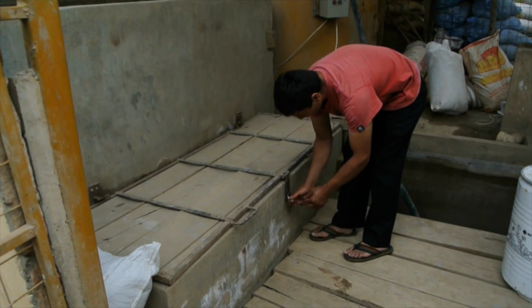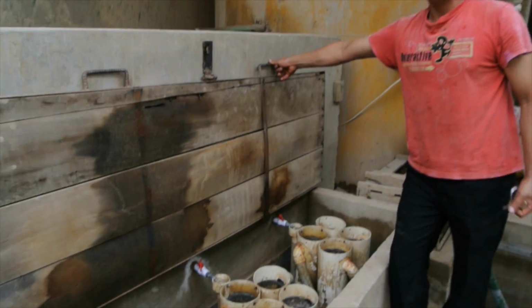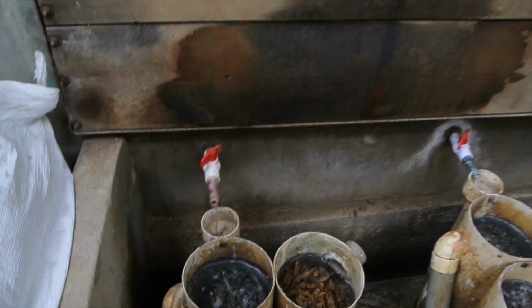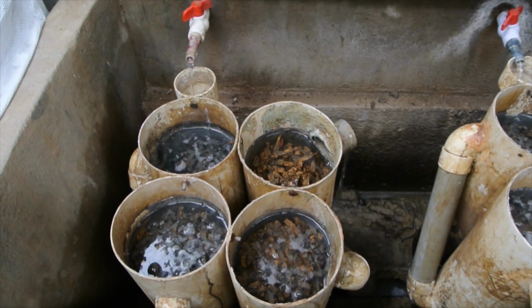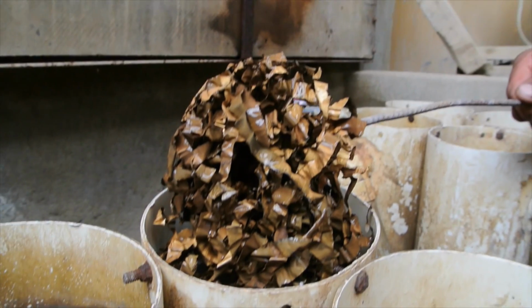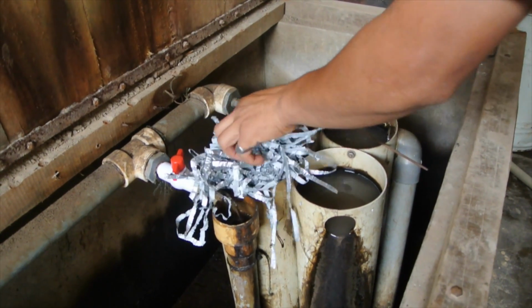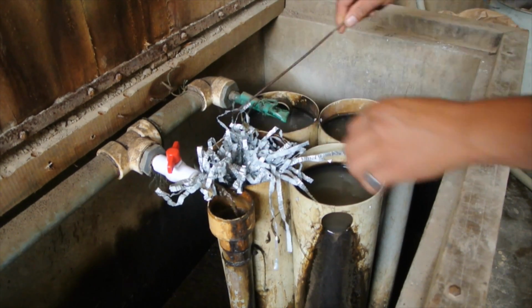Over 5 days of being agitated in a cyanide solution, the gold is dissolved and pumped through zinc shavings. The zinc precipitates the gold out of solution, turning the zinc from a metallic silver to a dull brown color. The zinc is continually replaced, ensuring that any gold in solution has a maximum chance of binding with it.